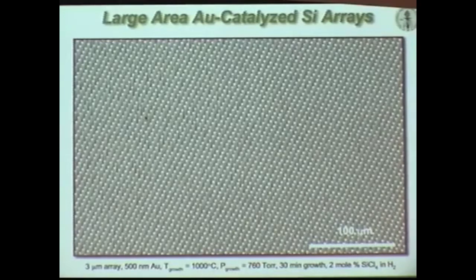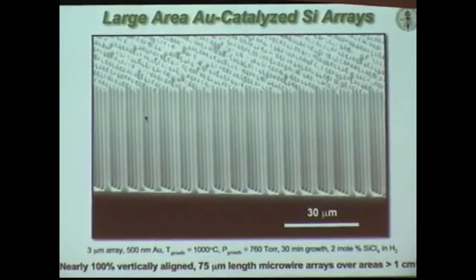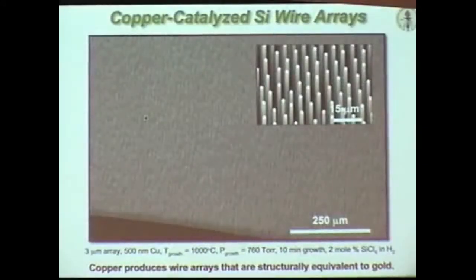A single crystal. And I know I've got 1, 2, 3 former Bell Labs people here who are ready to jump out of their seats because they know that I'm going to tell you that these are gold-saturated silicon samples at a growth temperature of 1,000 degrees, which they were told never let gold anywhere near silicon because it's a deep-level trap. And the only other option, of course, for growth is we can do it instead of with gold, we can do it with nickel or with copper. Still going to jump out of your seats.